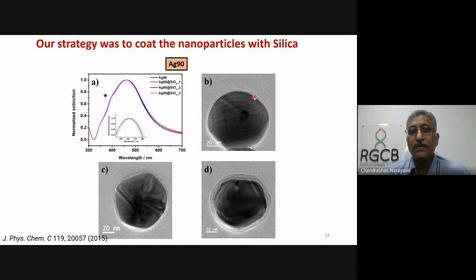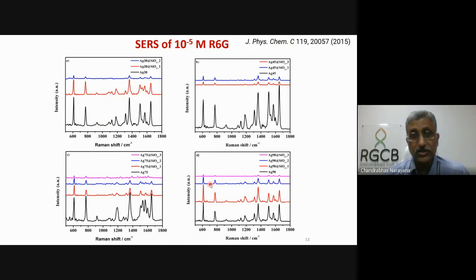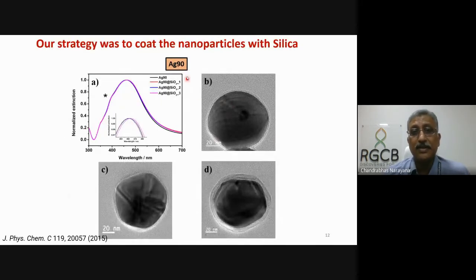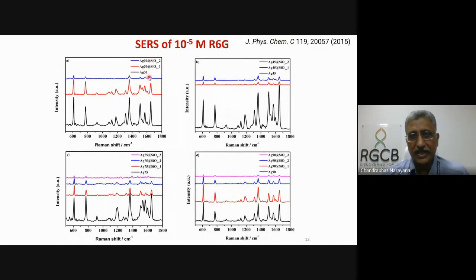So what we did is, we said we will not use any functionalization. What we will do is vary the thickness of the system. When we change the thickness by silica coating, a very special coating, we can control about 1, 2, 3, 4, 5 nanometers. You can see the thickness increases. Now, if I use any dye on top of it, I will get the signal from that. We also did one more thing: we changed the size of the nanoparticle. We went from 30 nanometers to 90 nanometers to study what happens in the system. Now you can see 30 nanometers, 45 nanometers, 75 nanometers, and 90 nanometers.